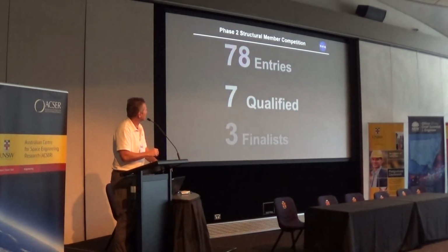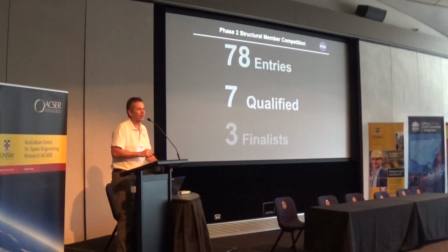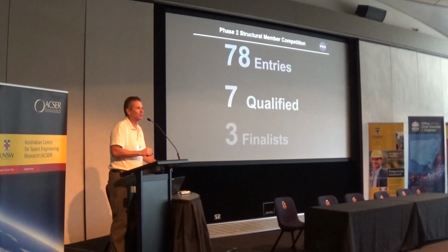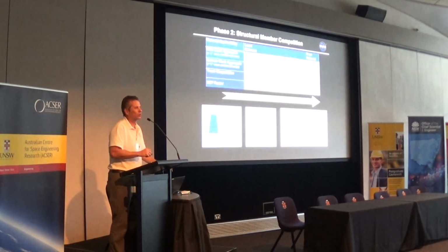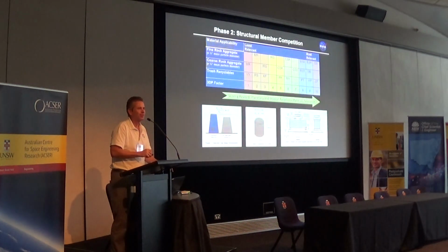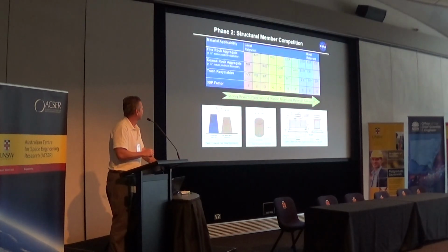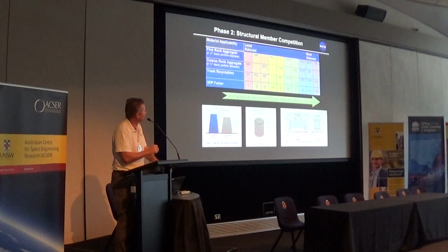We had 78 entries. The attrition rate is high in these competitions. 78 teams entered, 7 were able to meet the requirements to qualify to come to Peoria to do the competition, and only 3 showed up. And of those 3, only 2 were able to print. It's not easy. This is our table for materials. We give more points for indigenous materials. The more indigenous it is, the more points you get. Then we have a formula which multiplies the points. Here's the